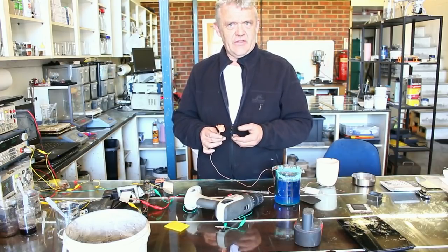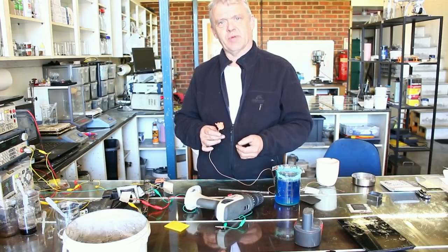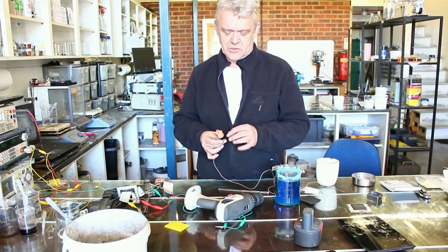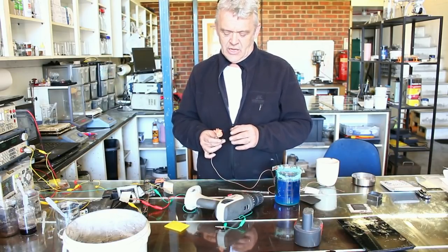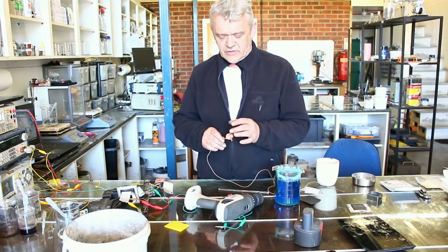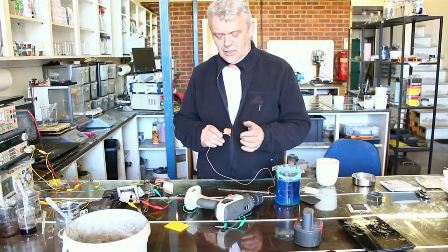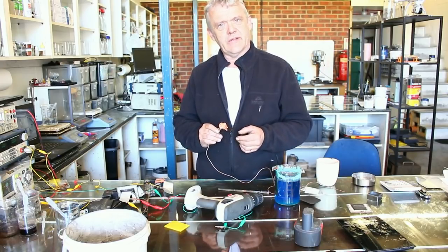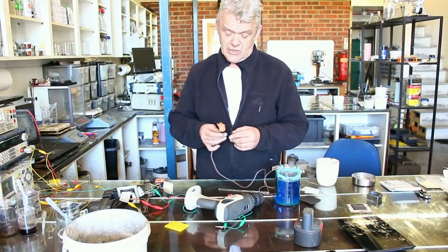Giving it a couple of days like that means that you get a lovely plate, particularly on something that's got a complex surface with lots of high points like this. If you have a flat surface, you can up the current density a little bit. Anything with this kind of intricate shape, if you want to follow the shape, you need a relatively low current density and lots of time. Just leave it. It'll do it all by itself.